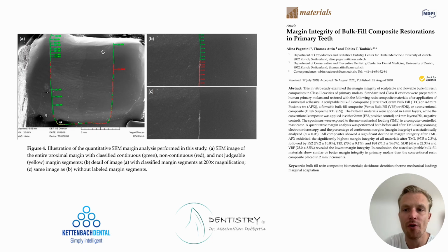At the same time, the study confirmed that thermal and mechanical stresses, such as those occurring in the oral cavity, can generally lead to some reduction in marginal integrity regardless of the material used. The authors interpreted these findings to suggest that bulk fill composites may represent a valid restorative option in pediatric dentistry. The simplified application technique does not appear to negatively affect the marginal integrity of the restoration, especially in the context of treating children where minimizing treatment time is often crucial. This may represent a significant clinical advantage.